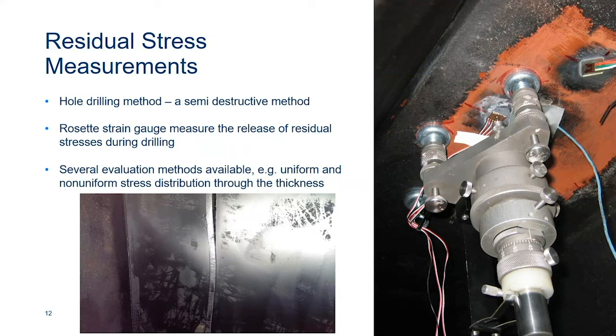You can see there are two strain gauges attached. The first one, with the hole drilling, is for measuring the residual stresses. The other one is just a dummy gauge to make us able to remove the measurements from the traffic that was running over the bridge during the testing. Whenever there was a car or a truck driving, we got huge changes in the measurements. So we need to remove this noise, you could call it.